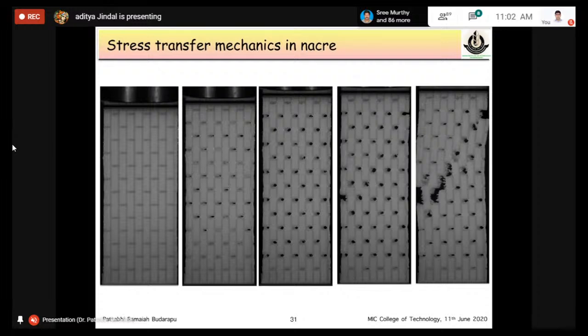Now we want to study the interfacial mechanics of this type of structure. So what we did is print such a brick and mortar type structure — you can see a hard brick material connected by the interface, which is a very soft material. When such an assembly is subjected to uniaxial stress, we observe that the tablets actually slide because of the presence of the soft matrix.